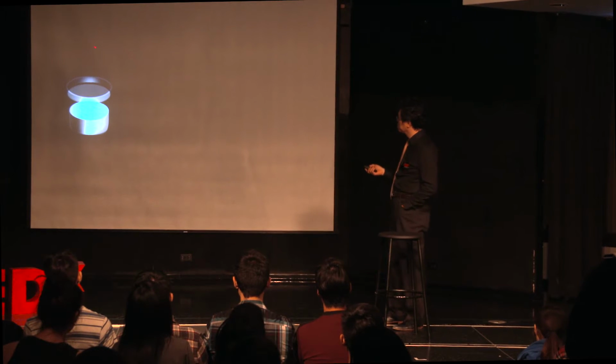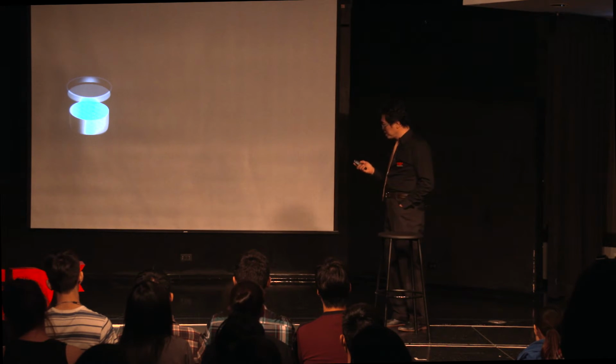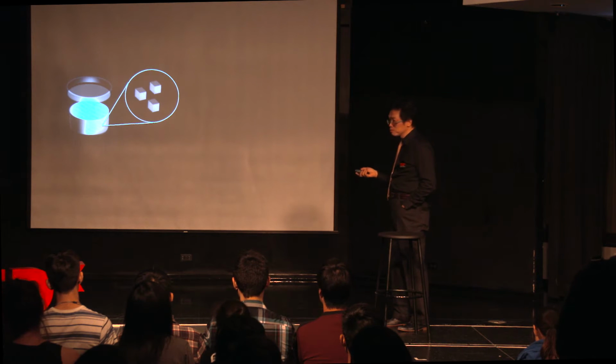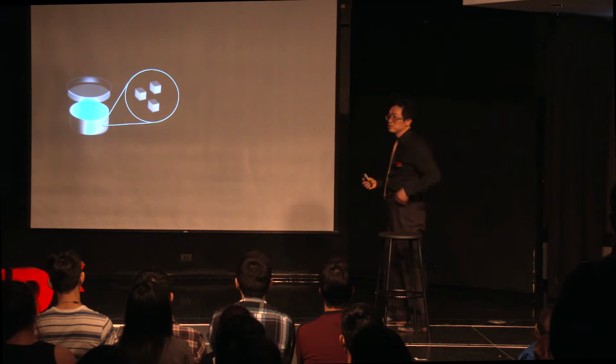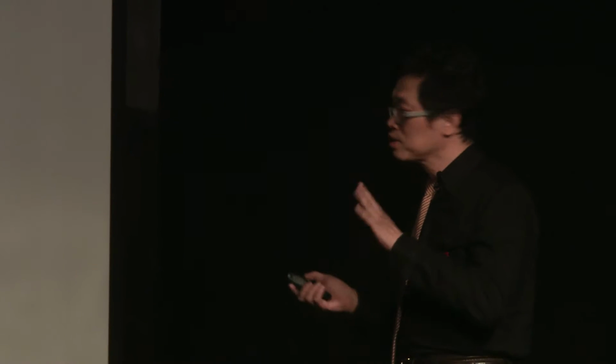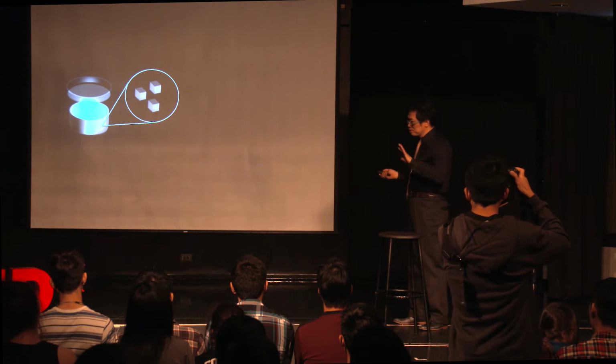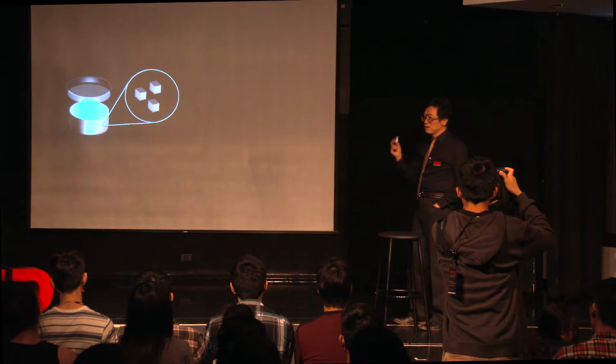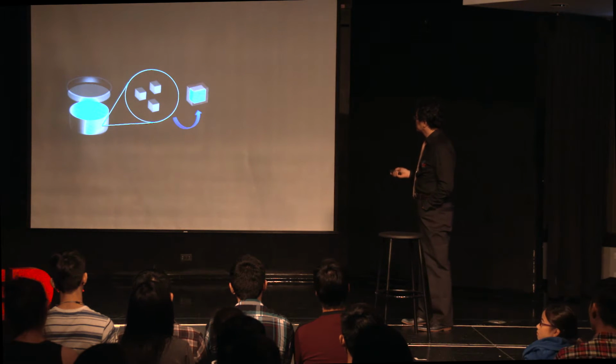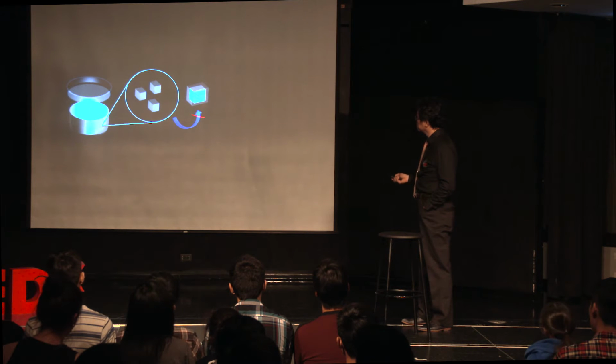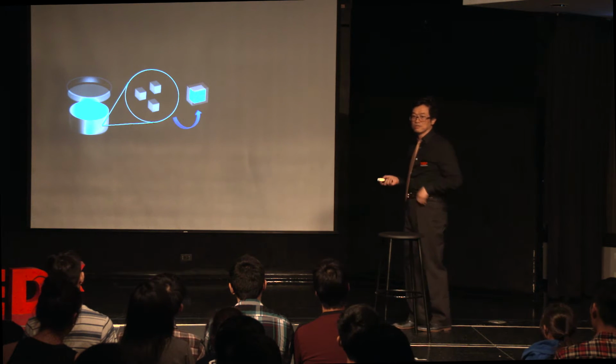It's actually pretty simple. You have a water solution, and you contain some, for example, sodium chloride, and then you just change their temperature and the solubility. And with ultrasonic vibration, you will fabricate very, very tiny crystals, right, by precipitation. And because of their surface charge, now you give them polymers, so the polymers will automatically attach on the surface.